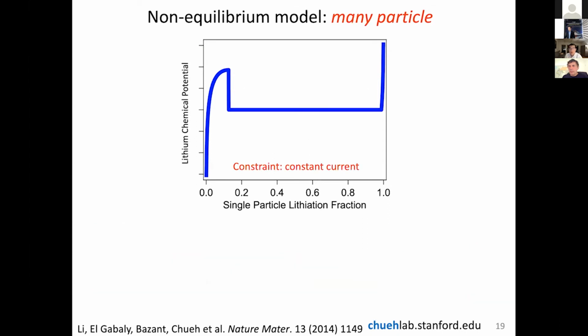Well, in the single particle case, you only need one nucleation event. However, in the many particle case, you need to have one nucleation event per particle. So if you have many particles, you need to have a constant rate of nucleation in order to maintain the current that you're asking the battery to accept or deliver. So now the situation is very different. You need to have particles overcoming this nucleation barrier at a finite rate. Okay, for example, a certain number of nucleations per minute.